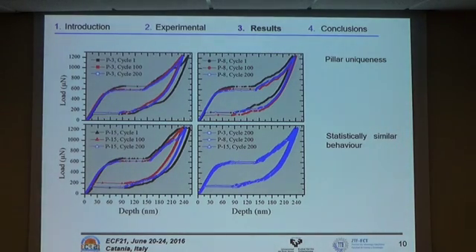But if you cycle the pillar, what we have observed is that more or less the behavior is maintained. And here I show you the behavior of 3 different pillars. Initially, after some cycles, there is a certain training. That means that we introduce some defects which get stabilized after a certain number of cycles. And then the situation gets more or less stabilized, and this is repeated for different pillars. I show you here only 3, but it is repeated in several of them. And after 200 cycles, it is observed that, statistically, although the statistic is not so large, they seem to have a similar behavior.